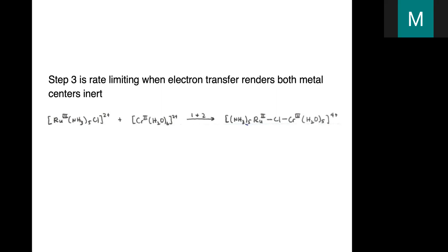So we're starting with ruthenium 3, 5 ammonias, chloride, and it's being reduced by chromium 2. Chromium 2 easily and rapidly loses water and allows chloride to form a bridged complex. And so this reaction is fast. The electron transfer reaction is then fast, but what's very slow is dissociation of this successor complex shown here, right? So after electron transfer, we've now got chromium 3, and that's going to be inert, so it doesn't want to dissociate. And ruthenium 2, as a second row transition metal, is also rather slow to dissociate its ligand. And so as a result, this product persists and can be isolated in pure form.